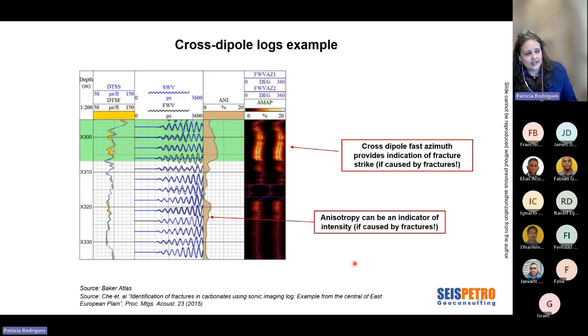This is just an example of a cross-dipole tool. It will give you the slowness, the DT of the slow shear and the fast shear, so you can plot them on the same scale, and if you color between them, you can see where you have more stress anisotropy. This is just the full waveforms here, and this is the calculation of anisotropy. You see more anisotropy at the top. And again, this could be caused by fractures if you're sure it's not caused by a stress anisotropy.